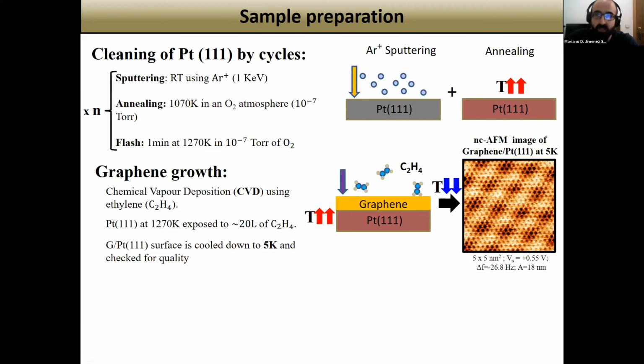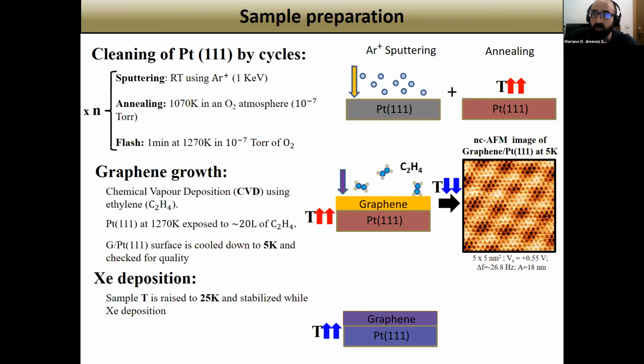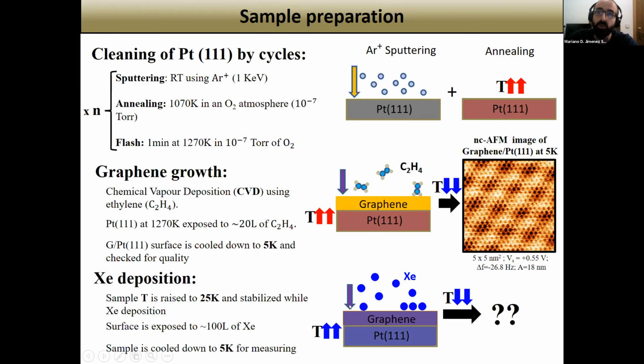The next step was the xenon deposition. In order to do it, we have raised the sample temperature to 25 Kelvin, and we have stabilized it during the xenon deposition, which consists in the exposure of the surface to a pressure of xenon. After this, we have again cooled down the sample to 5 Kelvin in order to perform the measurements.